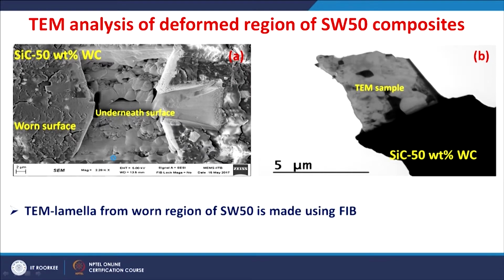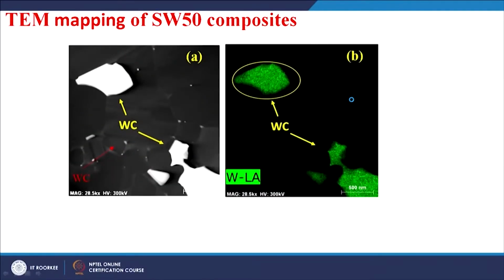To understand the origin of such behavior, the TEM analysis was done on the deformed region of the selected composite. A TEM lamella was made from the worn region using the FIB. So, this TEM sample was subjected to further investigation. So, this shows the silicon carbide grains and then tungsten carbide particles.